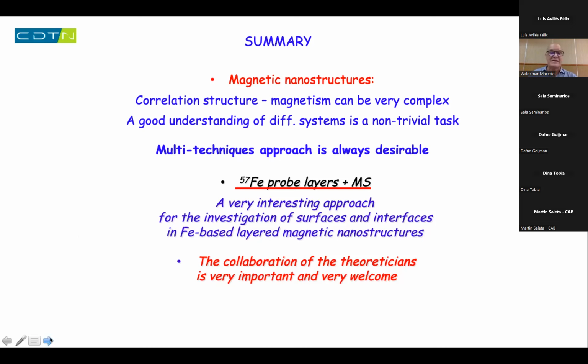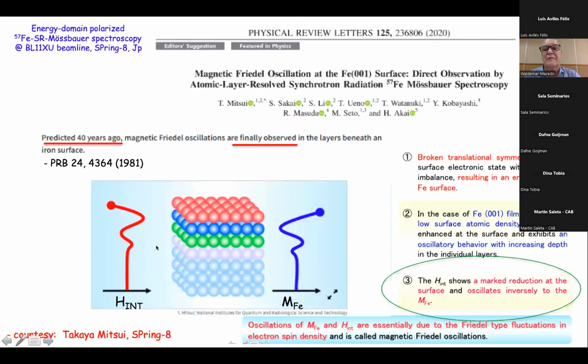I was running with this because I want to show you a little bit more of what we could do with a similar approach by using synchrotron radiation. I want to show you a few results. This is a very nice paper, work done at the Mössbauer beamline at SPring-8 in Japan by Mitsui, and they measured two years ago these Friedel oscillations at the iron surface. And these oscillations were predicted 40 years ago, and only now there has been this paper from 81,